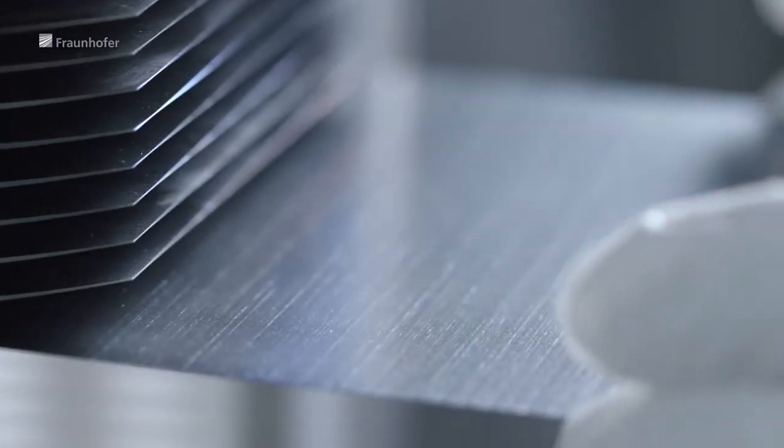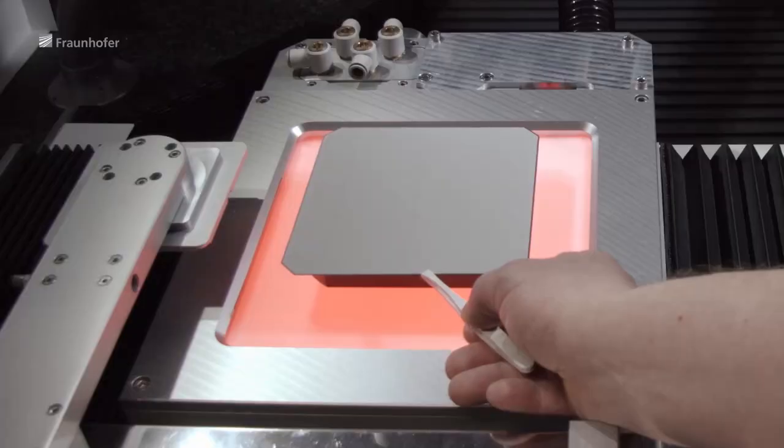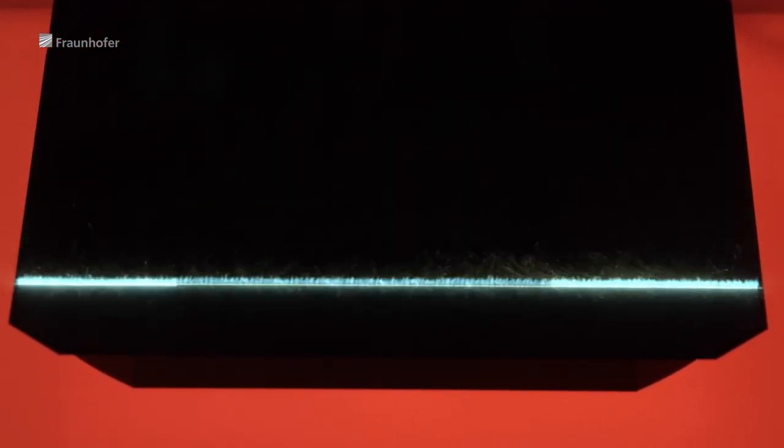Since this mirror is not conductive and separates the semiconductor from the electrodes, thousands of minute connections have to be made through this layer so that electricity can flow from the wafer to the electrodes. Fraunhofer researchers achieved this with laser-fired contact technology. Each of the approximately 100,000 contacts is created with a single laser pulse.